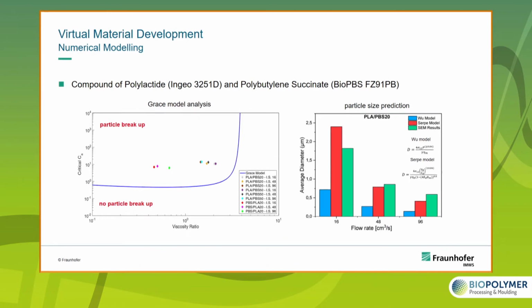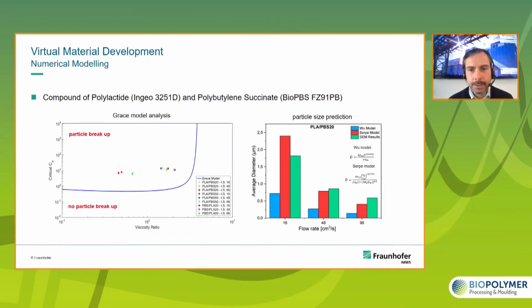To predict the final diameter of the microstructure, we used the WU model and the Serpe model. And as you can see on the right side, the Serpe model was much closer in prediction of the diameter of the droplets than the WU model, and this gives us certainty in the next step, which is the material modeling, meaning the real prediction of the final properties of our material.